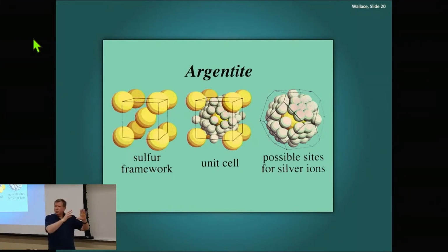So the sulfur structure is defining what's going on, and the silver is in this cage of the sulfur. But if we heat it up, the cage expands. If that cage expands, sometimes the silver can escape. It can move somewhere else in that particular mineral. And that's giving us this change in both structure and why we grow wires.